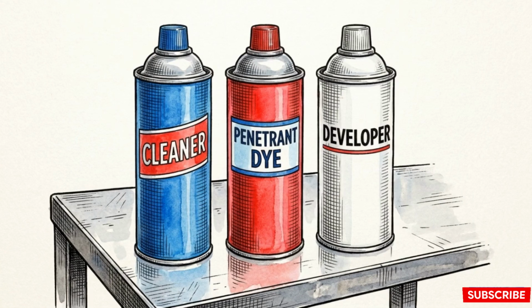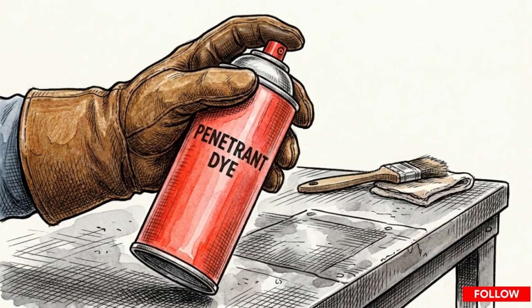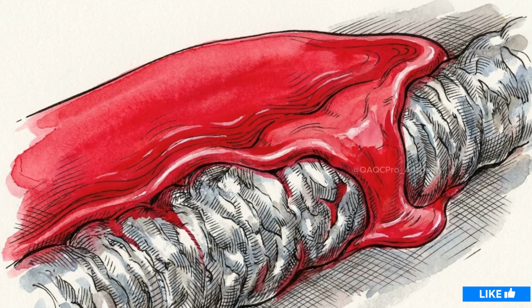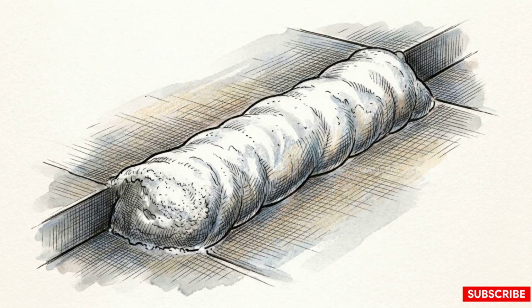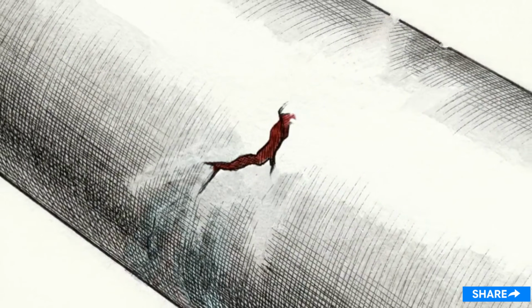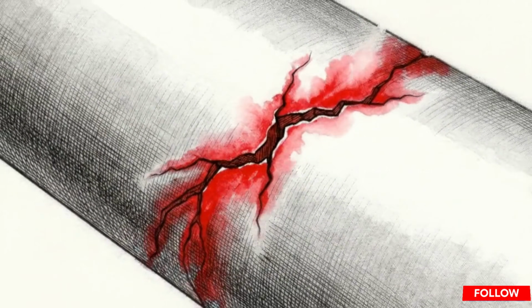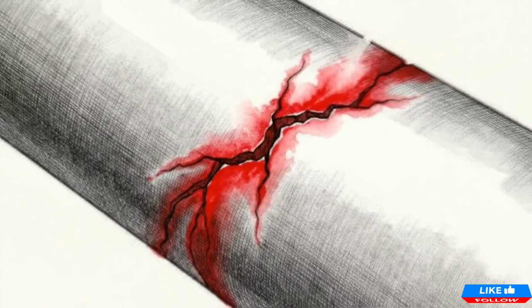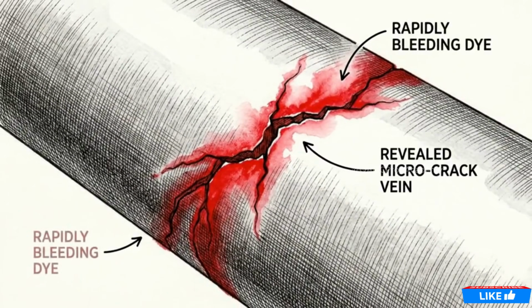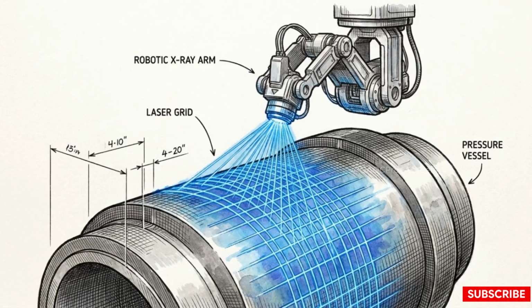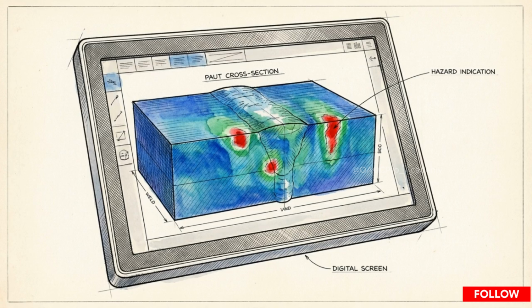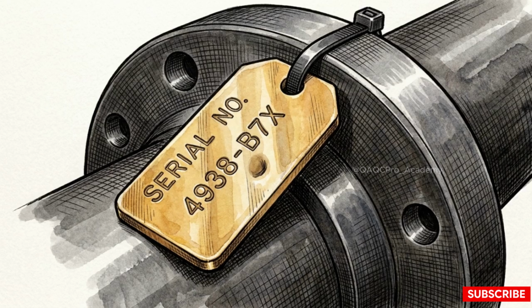Next, use dye penetrant testing to scan the surface for any microscopic flaws. This is a 3-step process. Spray on the penetrant dye, wipe away the excess, and apply the developer coating. Red dots or lines indicate the developer is pulling trapped dye from hidden cracks. A successful test shows a completely white surface with zero bleed-through. More advanced projects may require X-ray diffraction to measure internal stress, or deeper ultrasonic scans to check for internal voids. Rigorous testing provides the evidence needed to certify a pipeline component for high-pressure service.